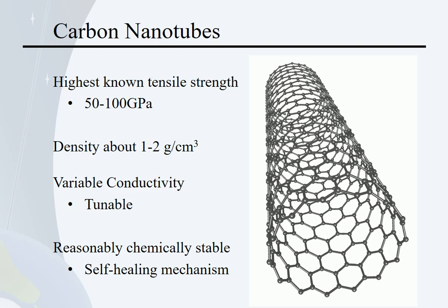The other thing they've got going for them is that they're reasonably chemically stable. They don't start oxidizing till around 600, 650 degrees C. They more or less don't react with most acids and superacids, and you have to be fairly aggressive in terms of your chemistry, even if dealing with plasmas, to get them to react. They also show a self-healing mechanism. If you've got them in an inert environment and raise the temperature, maybe in the presence of a little bit of carbon, any defects in the structure will spontaneously heal, either by bond rearrangement or by incorporating that extra carbon.